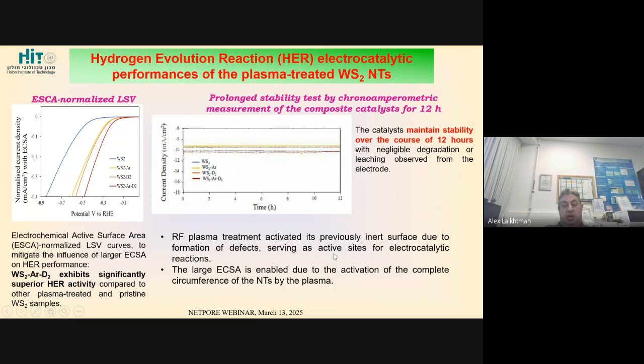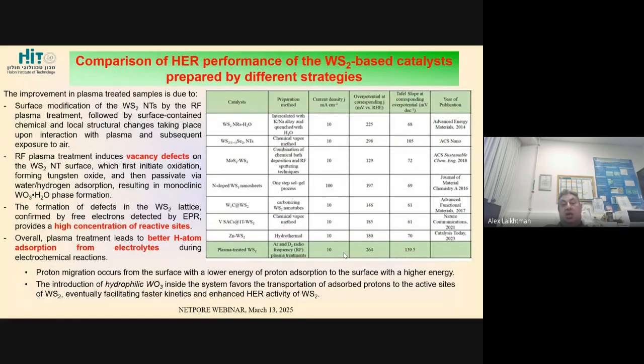So we proved in such a case that RF plasma treatment activated a previously inert surface due to the formation of defects, as we proved by EPR, and then these defects serve as active sites for the electrocatalytic reaction. Before going to another part, we still decided to compare our plasma-treated nanoparticles with other nanomaterials.